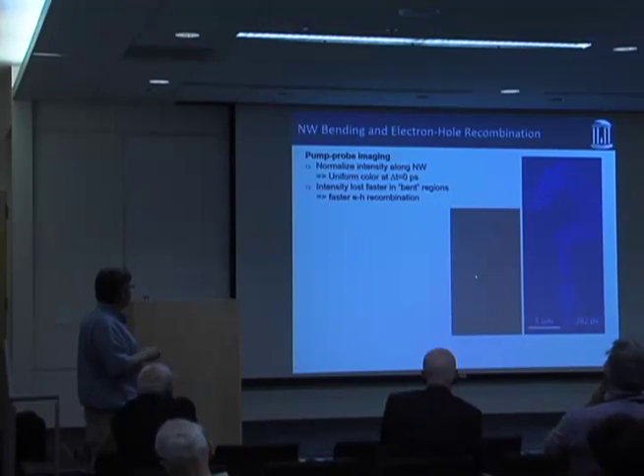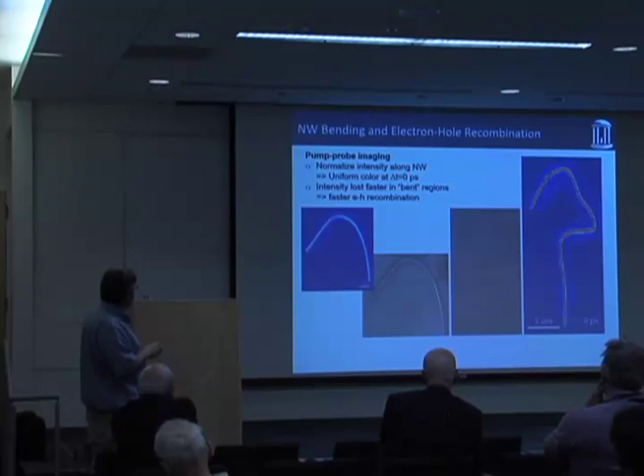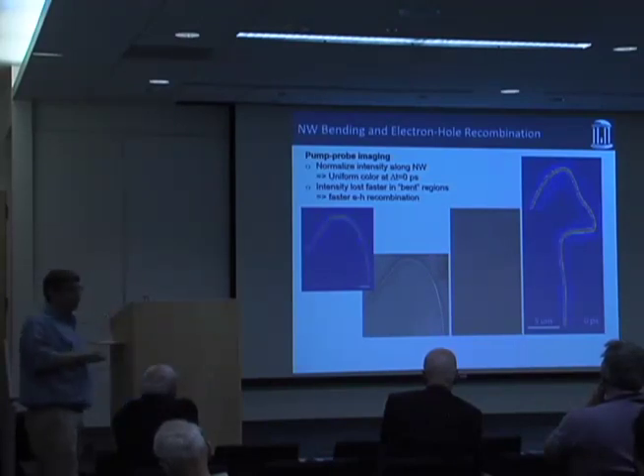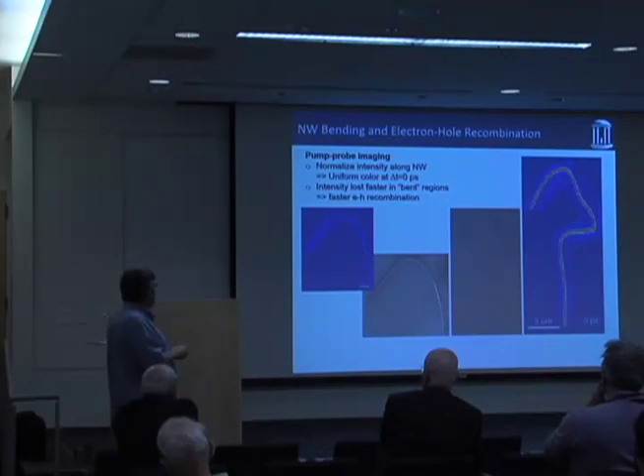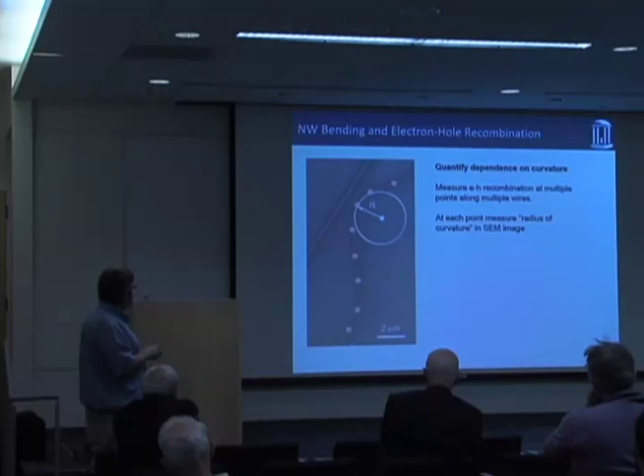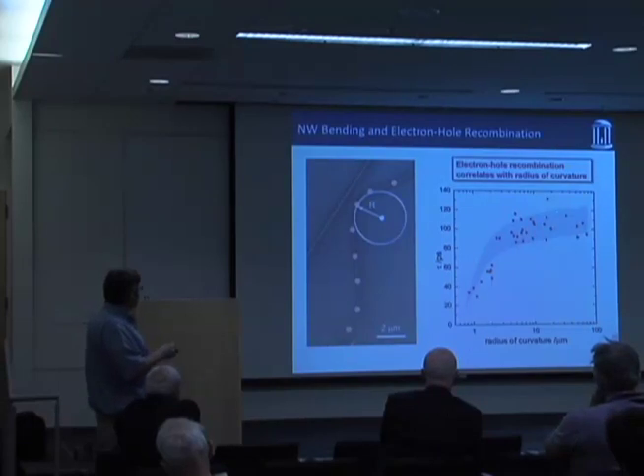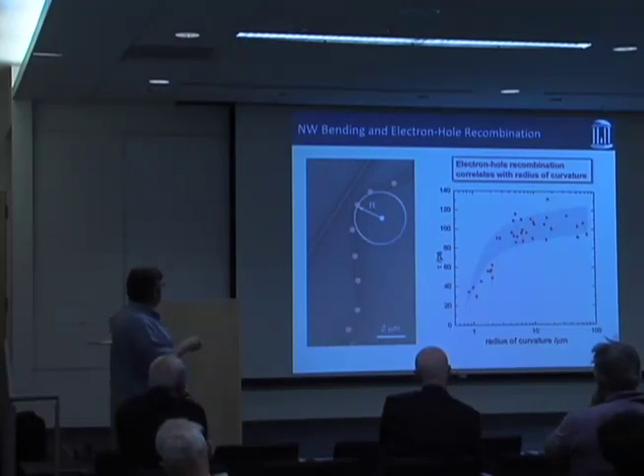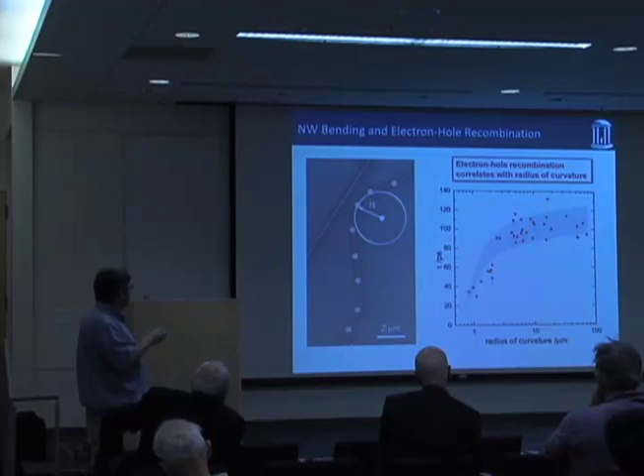So here's another one. And here's another one, does the same sort of thing. So everywhere we looked, wherever the wires were bent, the recombination kinetics were faster. And so we thought, okay, can we start to quantify this? We take the samples, and we know exactly what the structures are. At each point that we measured the kinetics, we also figured out what the radius of curvature was. And when you do that, you can see there's a clear correlation between the radius of curvature and the lifetime.